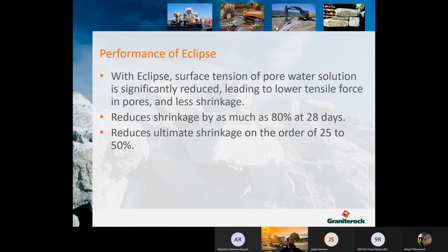So how does Eclipse help that? With Eclipse, the surface tension of the pore water solution is significantly reduced, leading to a lower tensile force in all pores and less shrinkage. So basically it cuts the surface tension of water to reduce that pulling force. It can reduce the shrinkage by as much as 80% at 28 days, and ultimate shrinkage in the order of 25 to 50% overall.